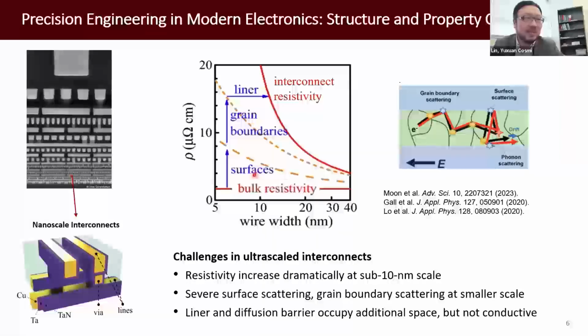It's related to surface scattering, that rough surface. Also, grain boundary scattering at this 10 nanometer scale. Copper is polycrystalline with very small grains, so an electron going through the grain boundary may scatter and lose energy. And then another degradation factor is that additional layer that's wrapped around the copper. People call it a liner and a diffusion barrier. We need that for reliability purposes. We need to avoid the copper from delaminating. We also need to avoid the copper atoms from diffusing into the dielectrics, so that will cause failure.